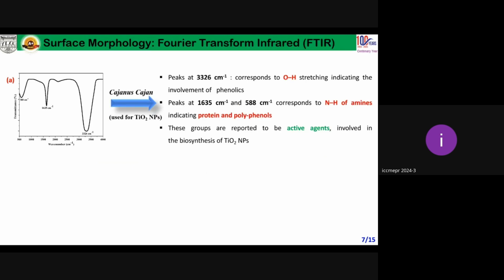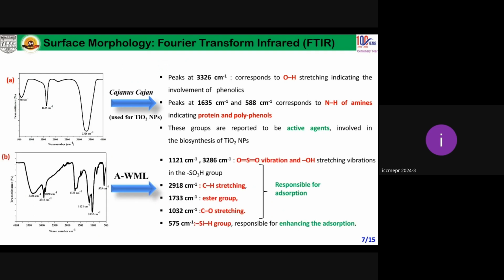For the characterization of the TiO2 nanoparticles synthesized using the Cajanus cajan extract, it was observed through FTIR that three distinct peaks were present. These peaks correspond to phenolic groups, proteins, and polyphenols, which are basically the active agents involved in the biosynthesis of TiO2 nanoparticles. And for AWML, FTIR characterization was done and different peaks were observed at different wave numbers, which correspond to different functional groups which are basically responsible for the adsorption process.